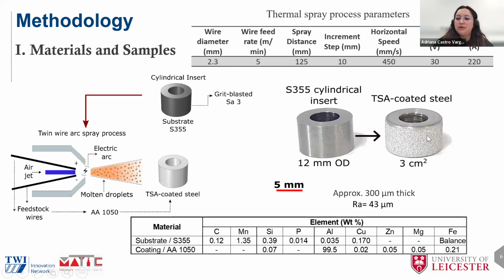The coupons have a thickness of around 300 micrometers and a high roughness of around 43 micrometers. On the bottom, we can see the element composition of the material of the substrate and also the coating. In this case, we are going to evaluate this coating for the immersed zone, and we have 99% of aluminum.